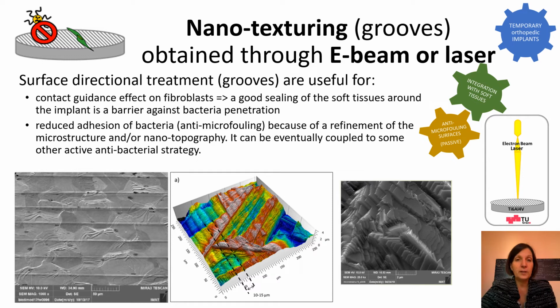And another type of treatment is through E-beam or laser, and in this case we can obtain some grooves on the surface. And these grooves are very effective in order to enhance the adhesion of fibroblasts and to orient the fibroblast in this direction through a contact guidance effect. So this type of surface is useful for temporary orthopedic implants, and it is able to enhance the integration with the soft tissues. And we can also see that because of the laser or E-beam treatment, we can get again a nanostructure of the surface with these sharp steps. And we have an anti-microfouling effect, so we gain a passive action against biofilm formation.